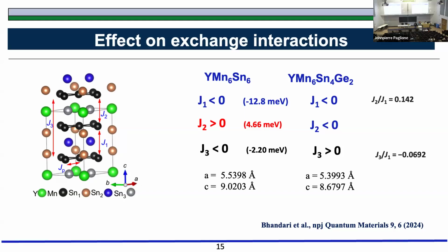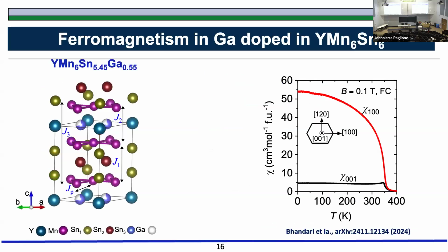Now, what after that, right? So then I told you that you can put gallium or indium in place of the tin. That's what we tried to do next. Let's put in a little gallium. Now, let's not just make the isostructure. Let's change the electron count also and see what it does. Then we tried to grow this with gallium doping, but with gallium doping, it's very hard. Again, this is probably a chemistry-related question, that gallium doesn't want to go too much into the system. We could put in at maximum maybe about 0.55 or slightly more.